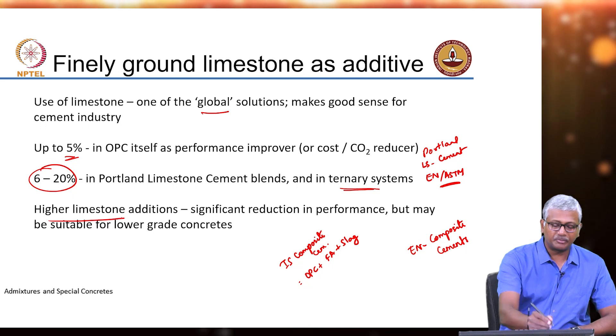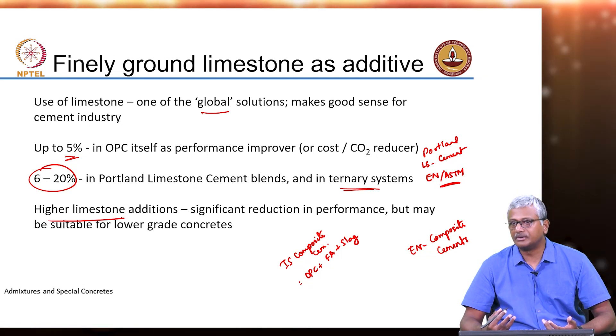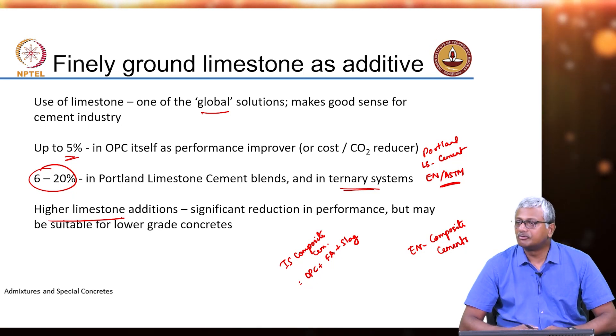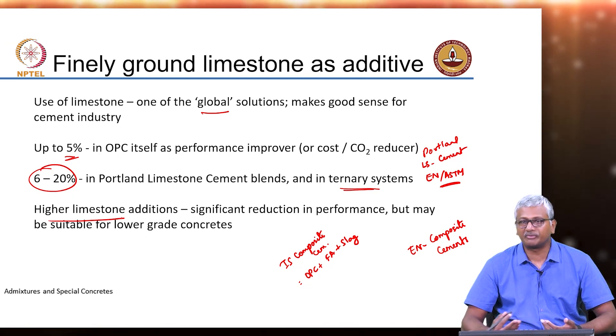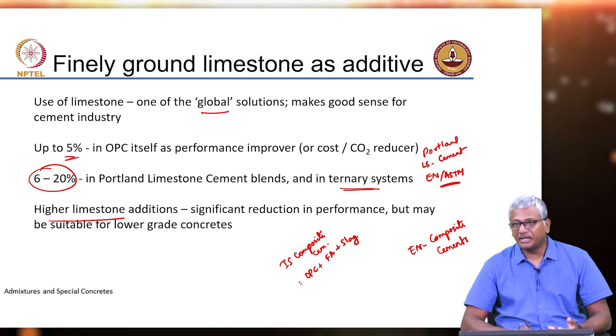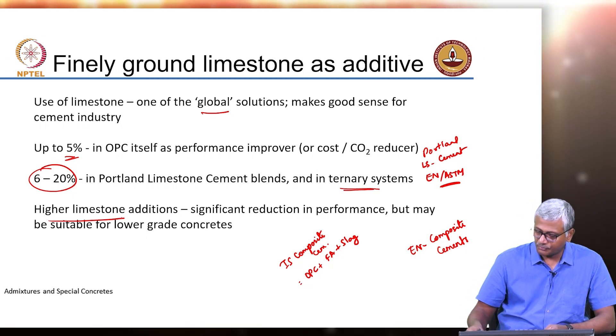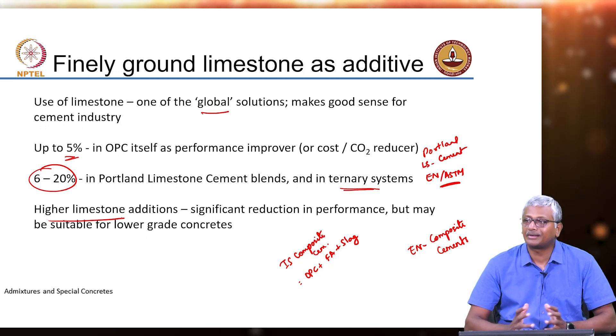If you go higher than 20% limestone, you are basically reducing the amount of reactive species available in your cement, so you will get a significant reduction in performance. Nevertheless, for low-grade concretes like residential construction using 20–25 MPa concrete, it is still possible to make concrete with very high levels of limestone replacement. We will talk about that briefly later, and with that we close for today and resume our discussion tomorrow with how limestone interacts in a cementitious system.